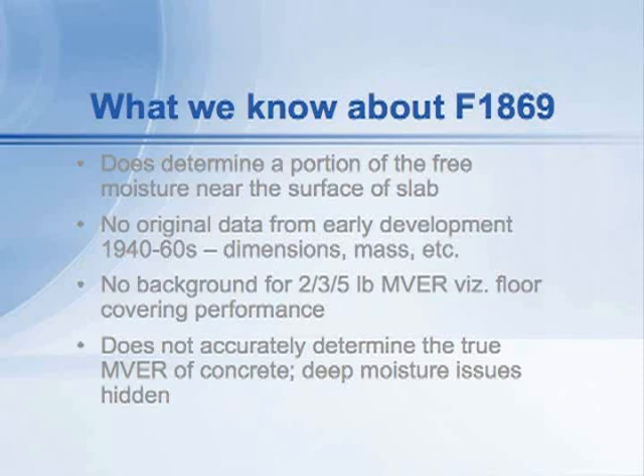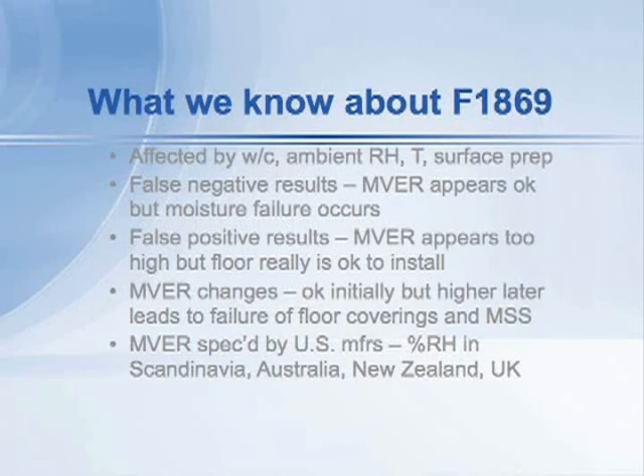We know that deep moisture issues are actually hidden and not seen by this test method. On the next slide, a few more points. We also know that the calcium chloride kit result is affected by water-cement ratio — the mix of the concrete actually has an effect on the results of the test. The ambient relative humidity and temperature affect it. If you're measuring the calcium chloride value on a day that's cooler and drier, you'll get a low result. On a warmer day or a damper day, you'll get a higher result.